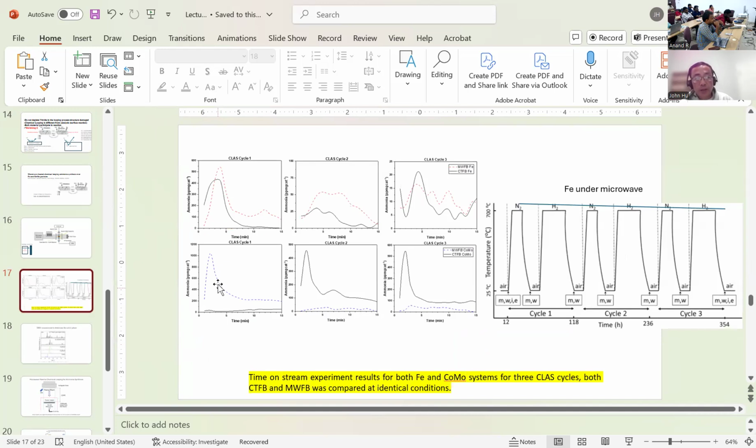The first one is easy, for ammonia to come out. And here, the ammonia comes out and then drops, and then more ammonia comes out. So you have two peaks. That's all related to this shrinking core model diffusion. Very good question. And then later on it becomes more difficult. The third, they show up as if they disappeared, and then another peak.